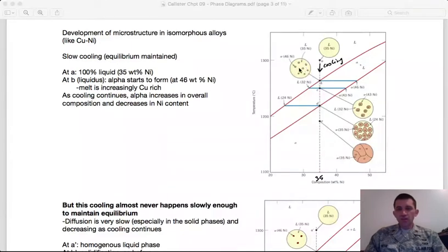And so in the melt, we're going to nucleate various grains of alpha phase, right? We'll have groups of atoms that bump into each other and happen to stick. And since we're cooling down, they're less likely to unstick, and so more atoms stick and those grains grow. Right at this boundary, I'm making alpha phase. I draw my tie line across and drop it down. I see that my alpha phase is 46% nickel. So I have these high nickel content alpha grains that are forming.